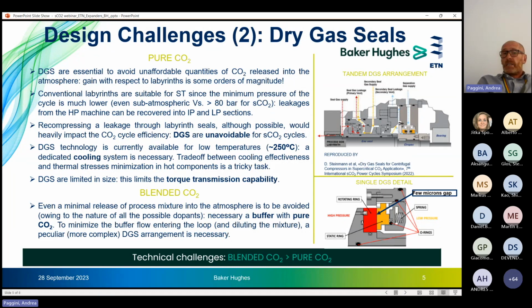The problem is that the current drag seal technology is limited in temperature. We are saying the maximum temperature is around 250 degrees C. Drag seal suppliers are working a lot to push up the temperature limitations, but as a matter of fact, at least in the short to medium term, no viable option other than drag seal cooling exists. And so it should be somehow intuitive that finding an optimal compromise between conflicting requirements like cooling effectiveness, cooling flow minimization, and limitation of the thermal stresses induced in the hot components is a tricky task. Probably this was the thermal management challenge in the slide question that was answered by some of the people. In this sense, it's definitely a correct answer.